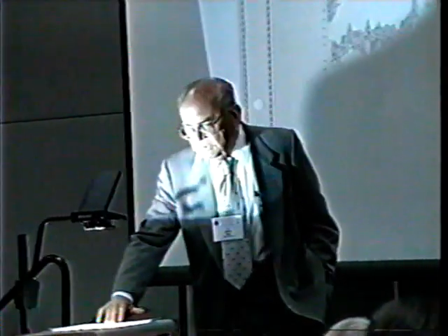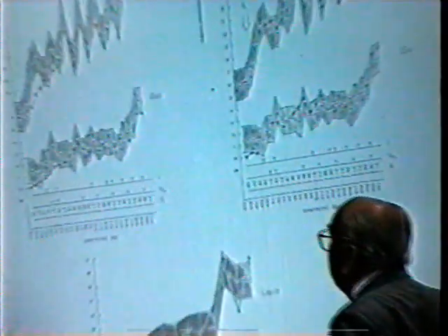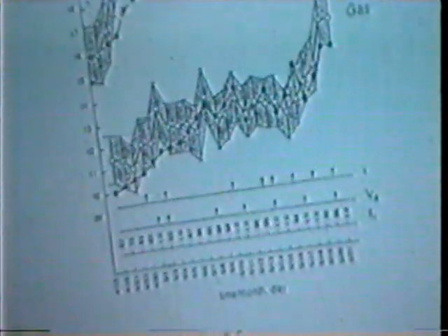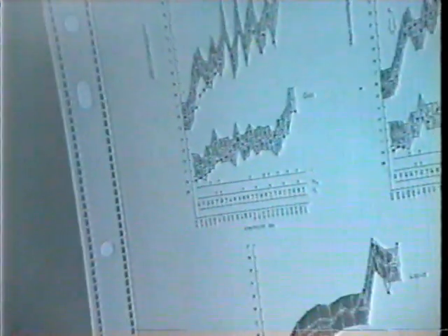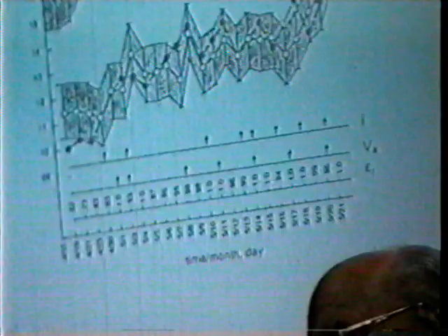Again, I'll show you typical results, what one can see. In this upper one, you see evolution of tritium on film smooth electrodes. That means electrodes which were co-deposited, but at very low current densities. It was saturated with deuterium to start with, but at much below the limiting current.